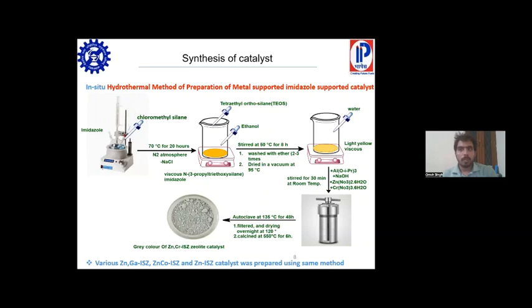I have synthesized the catalyst via hydrothermal treatment, in which imidazole and chloromethylsilane were homogeneously mixed at 70 degrees for 20 hours in an inert atmosphere. After that, tetraethyl orthosilicate and ethanol were added, and stirring continued at 50 degrees for 8 hours. Then washing with ether and drying in a vacuum at 95 degrees Celsius. After that, water, aluminum isopropoxide and different metal salts were added, and the solution was stirred at room temperature for 30 minutes. Then the solution was autoclaved at 135 degrees for 48 hours. After that, filter and dry overnight, and then calcine the material at 550 for 6 hours to obtain the gray colored bimetallic zinc chromium supported imidazole catalyst. In the same way, various monometallic and bimetallic imidazole supported catalysts were prepared.